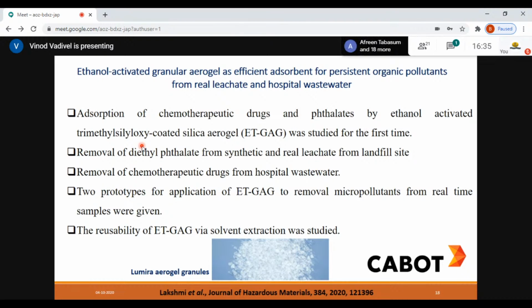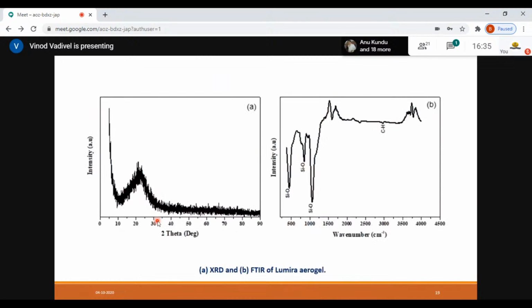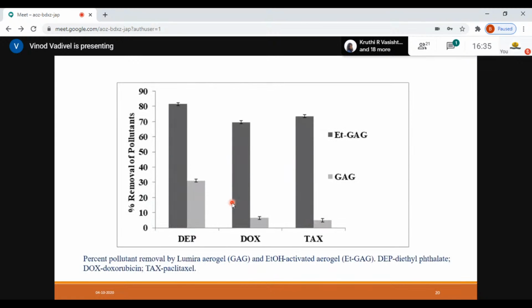Look at how many problems there are with microplastics. So we wanted to work with hydrophobic coatings, silica aerogels, and it really worked well. The removal efficiency was so high, and there were also reusability possibilities. You can see right here it's an amorphous phase. We confirmed that using XRD, and FTIR also confirms the functionalization of the materials.